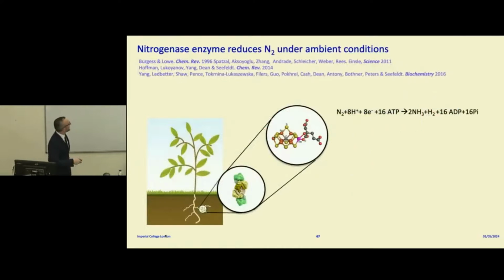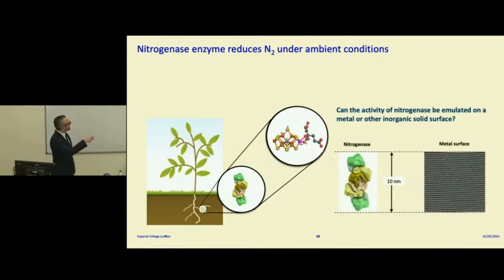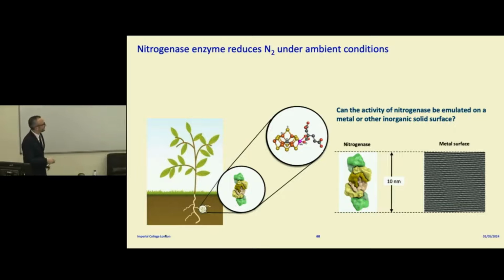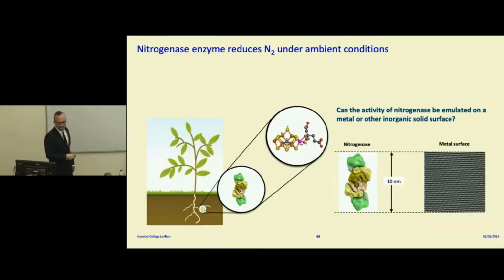Conversely, as already mentioned, the nitrogenase enzyme can do it under ambient conditions. The thing about nitrogenase is that each catalyst has a huge footprint, and you can pack a lot more active sites onto a metal surface. Each dot here is an individual metal atom, so you can get much higher rates if you were to use an metal surface instead.